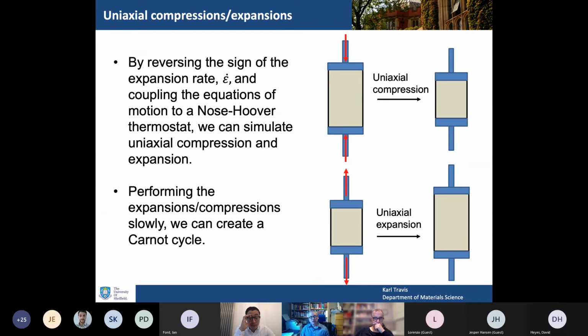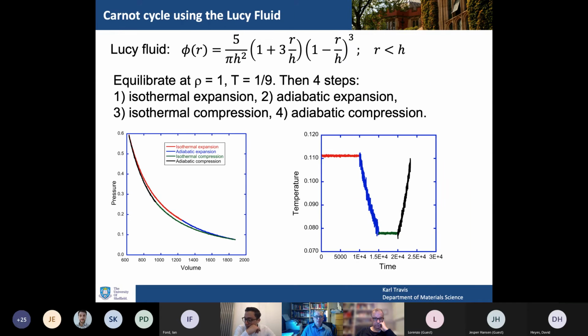Very quickly, I'll finish on the very last application. It's very much related. The motivation here was to look at closed die forging of metals, and I wanted my student to get a first understanding of uniaxial compression by looking at uniaxial compression of a gas. By reversing the expansion rate so it becomes negative, and coupling the equations to a Nosé-Hoover thermostat, you can simulate uniaxial compression and expansion, as well as adiabatic expansion and compression if you knock off the thermostat. So you can use that to generate a Carnot cycle.